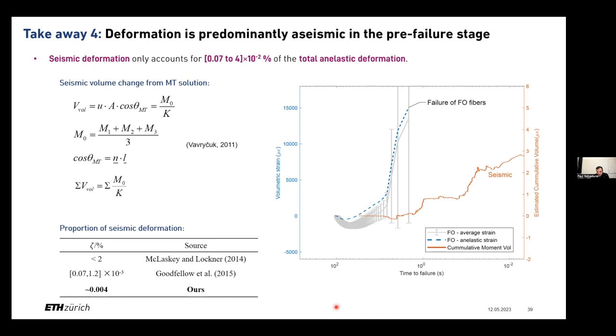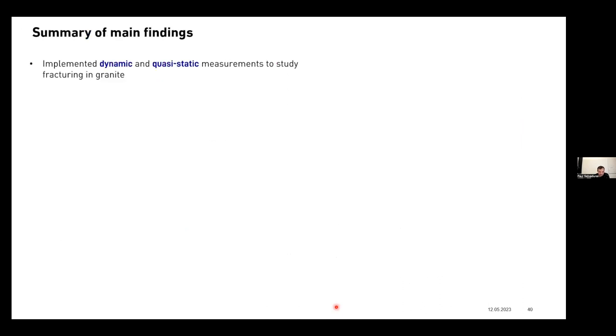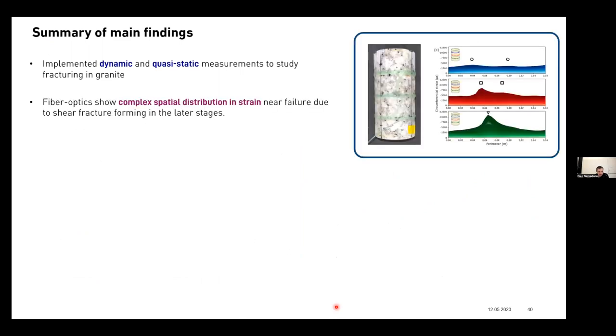So I'll summarize it into these last few points here. We implemented dynamic and quasi-static measurement systems to study the fracturing in a granite sample. We did this because we're downscaling the exact technologies that we use one scale higher in the underground rock labs. And with these two technologies, we were able to firstly see a more complex distribution of strain that was not visible before and only inferred from XRCT measurements and very small samples. So we're able to constrain this to a larger degree and see these interesting growth patterns and strain heterogeneity, as you see in this one figure.